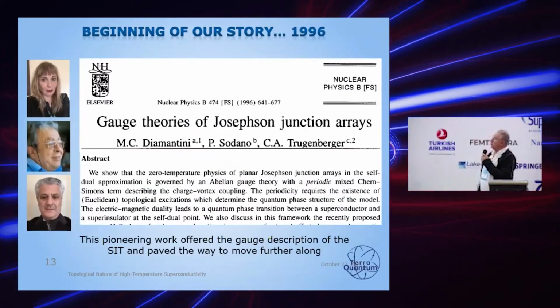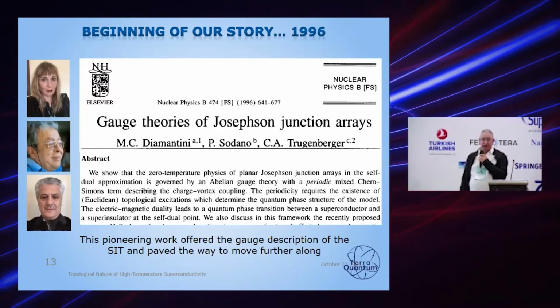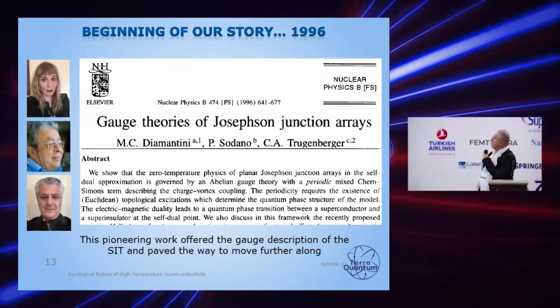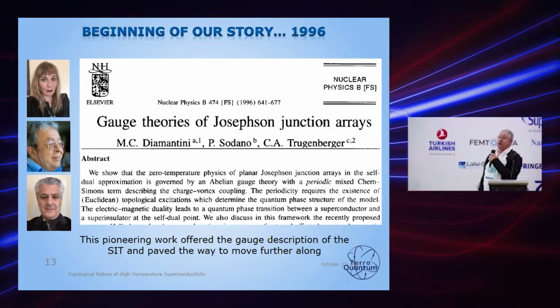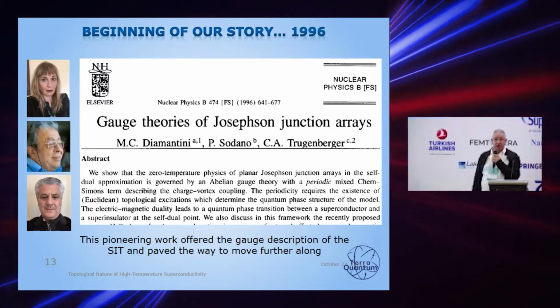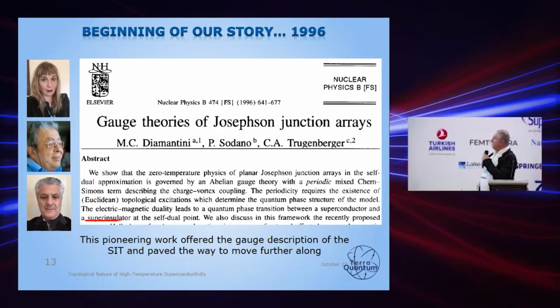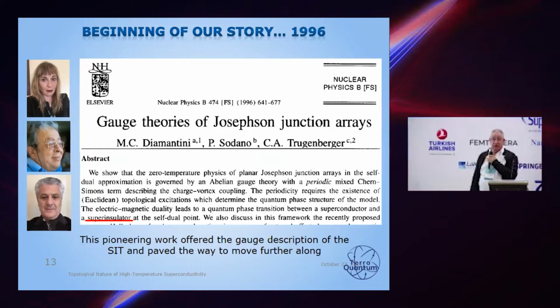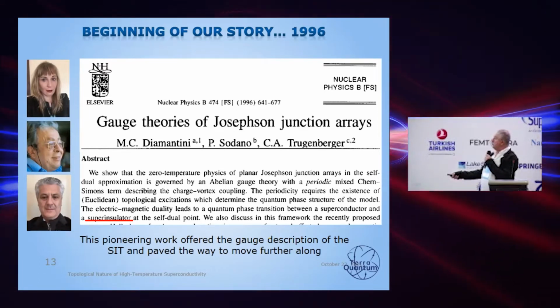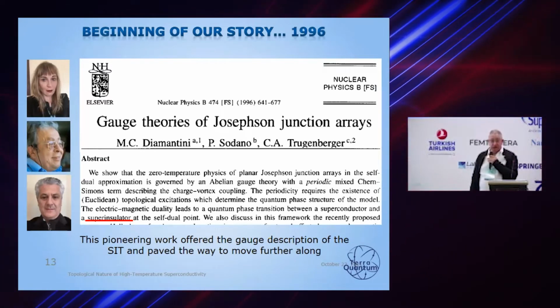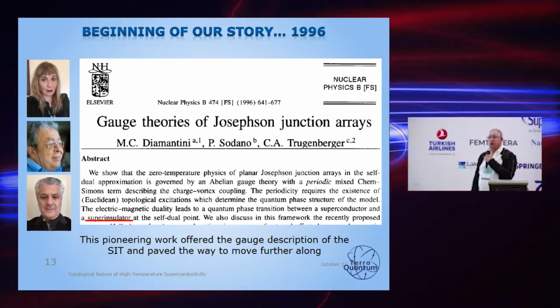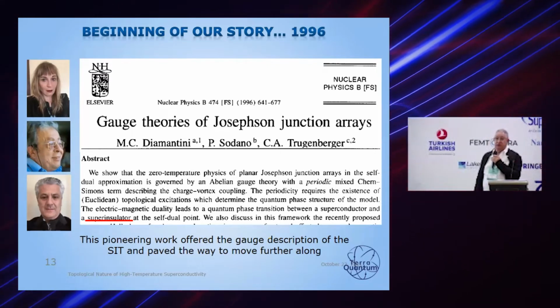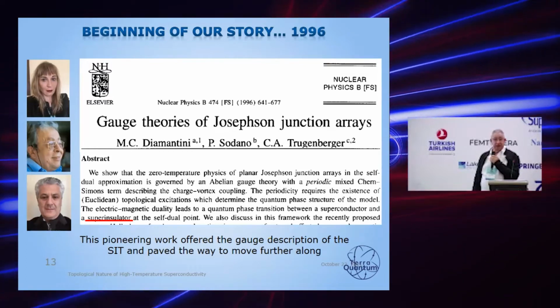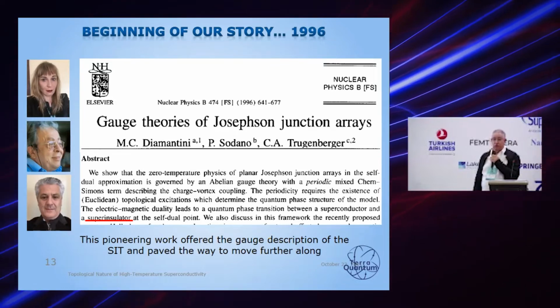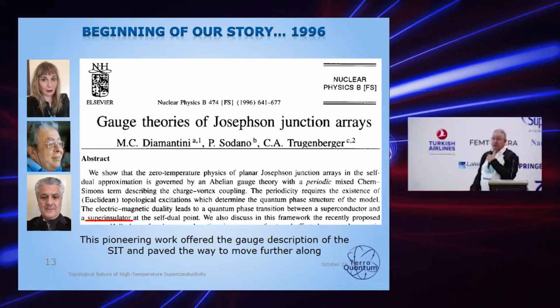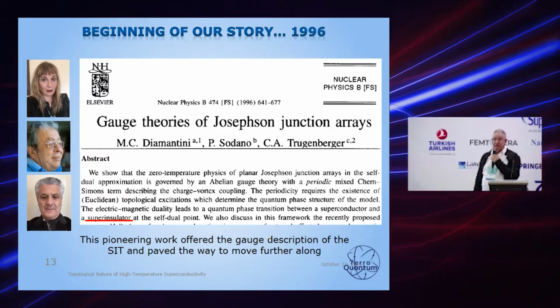And then there was an absolutely fantastic, pioneering paper written by my collaborators, who investigated the superconductor insulator transition in the very well established experimental system of a Josephson junction array. What they beautifully found was that the electric magnetic symmetry recovers completely, at least at zero temperature, and that a new phase, which they called a super insulator, appears on the insulating side of this transition. This super insulating phase is an absolute opposite, or mirror twin, of superconductivity, meaning that if in a superconductor we have infinite conductance, then in a super insulator, by the same token and with the same accuracy, we have infinite resistance. And they looked at that as indeed the duality between vortex and Cooper pair behavior.